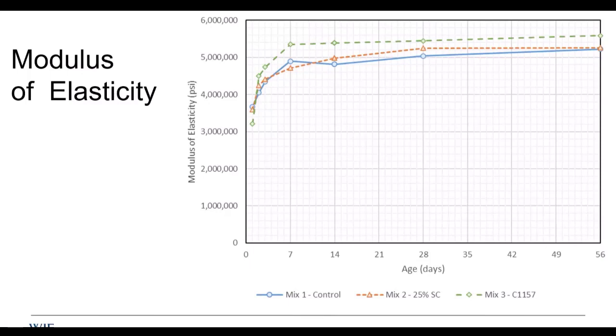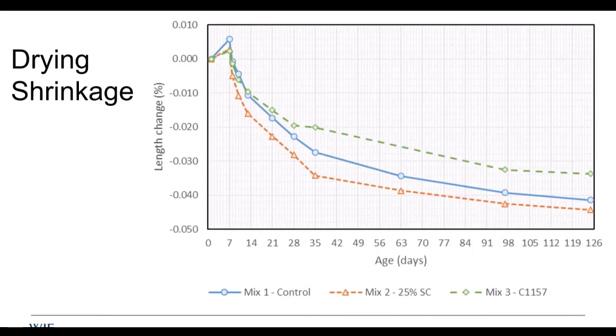All of these things are important, but we so often focus on strength, and strength, as you know, is a parameter of limited importance when working with mixes. It's important, but it's overemphasized because it's easy to measure. Things like bleeding, heat of hydration are often much more important. Drying shrinkage, we got less with mix 3. So a good finding there.